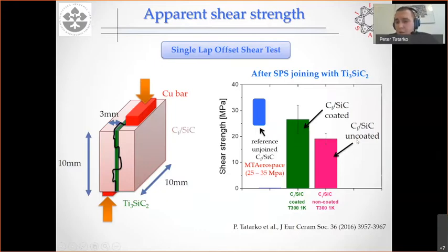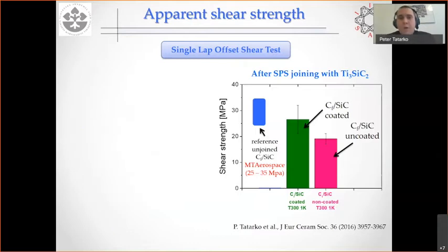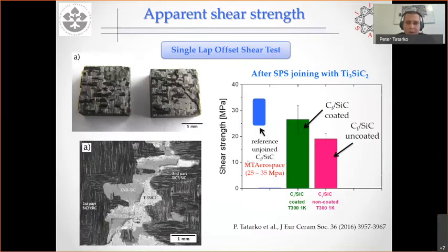In case of uncoated, the strength was a little bit lower, and we believe that we got this higher strength for this case just because, if you remember, as I said, this filler was better integrated with the matrix because it filled up the cracks and it healed up the cracks. So the filler was better integrated with the matrix. That's how we explained this higher strength.